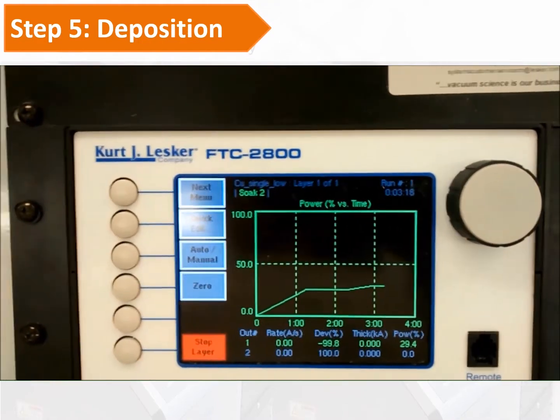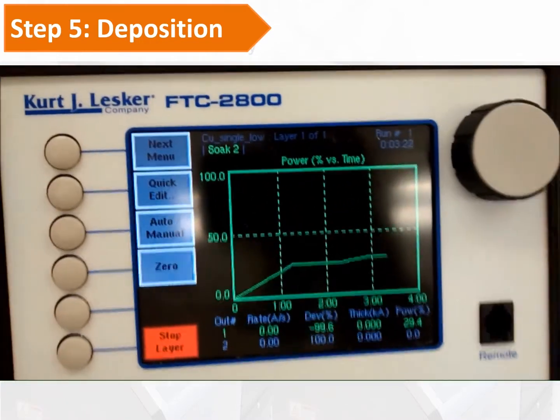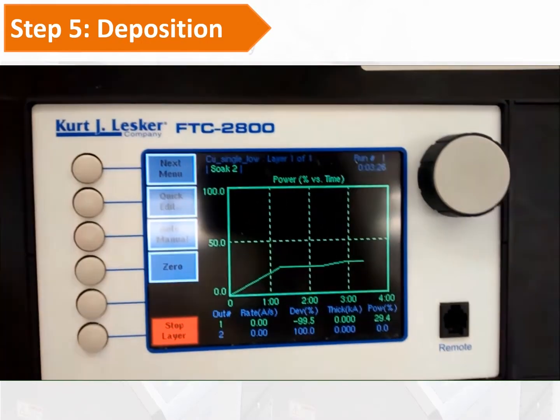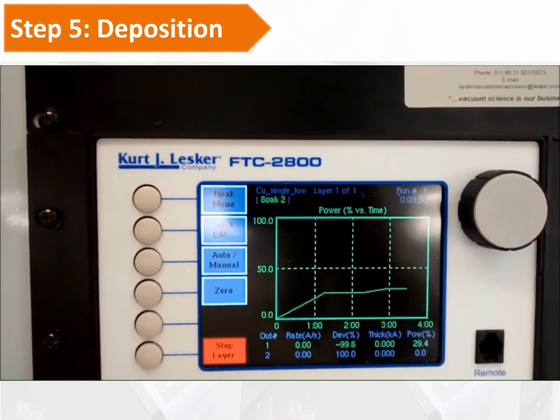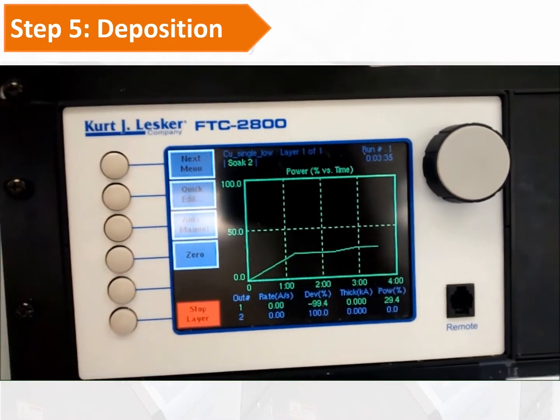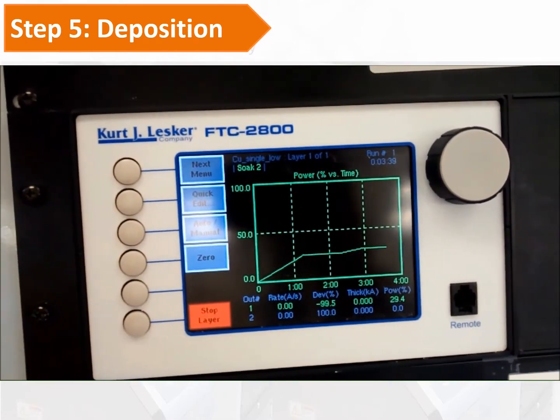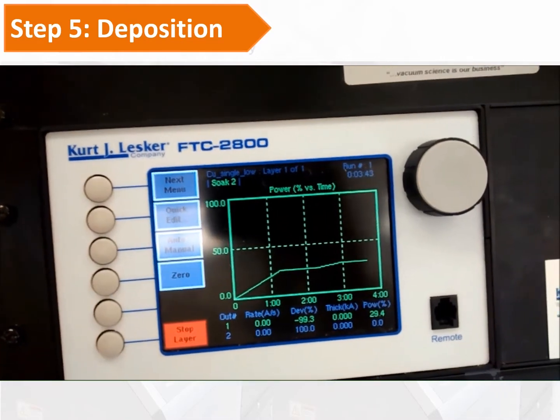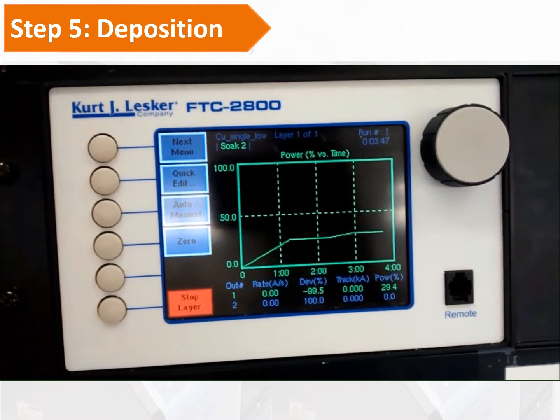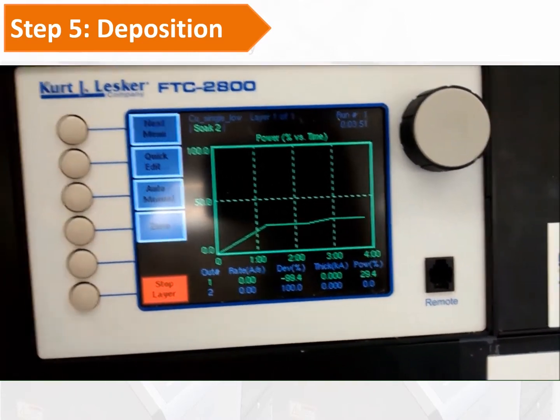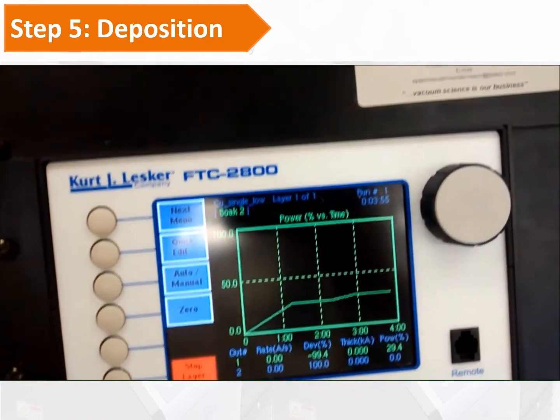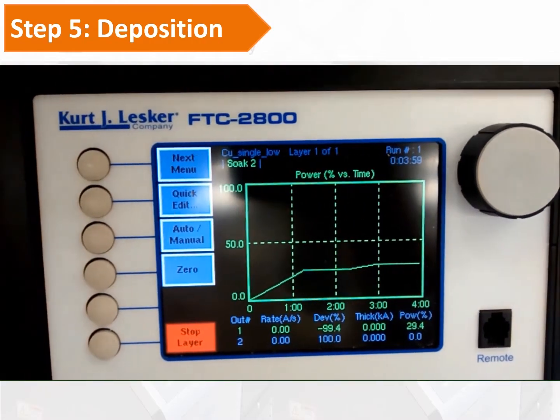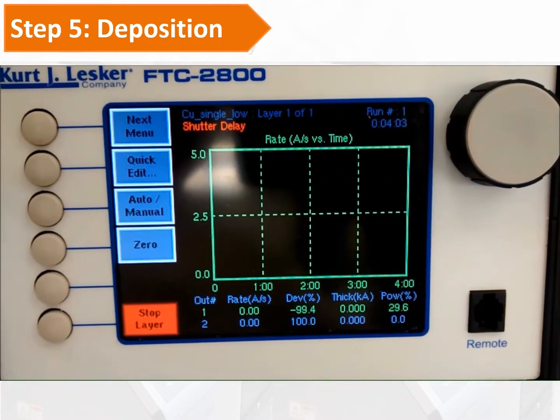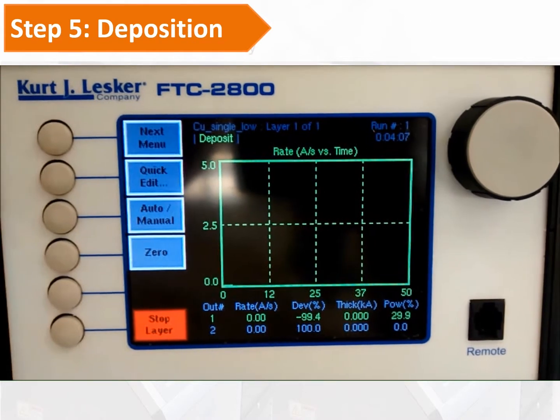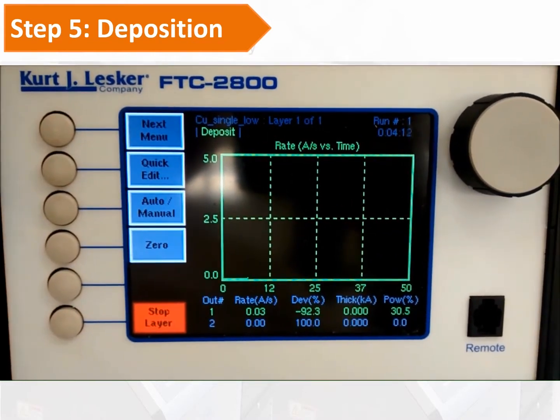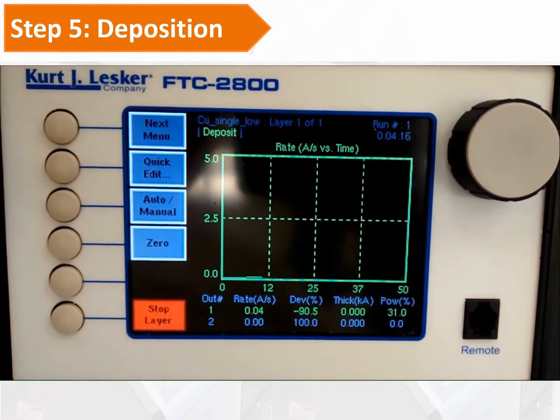And now we just wait to finish the preconditioning phase. So it is in the soak 2 phase. Okay, the shutter is opening there, and the deposition starts. And you may find the power will keep increasing, and the rate will also increase to the set values.